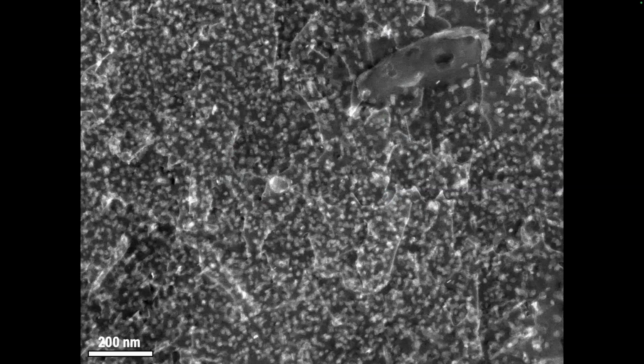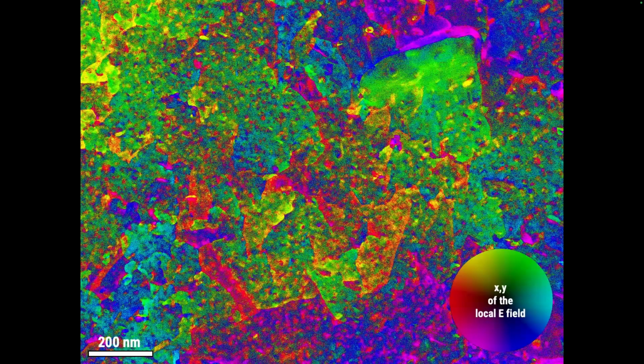This is the alloy viewed with dark field. You can see we have precipitates, dispersoids, and a lot of dislocations because it's 2% plastically deformed. And this is the DPC image. What you are seeing here is the electric field components, X and Y, in this specimen at the local sites.